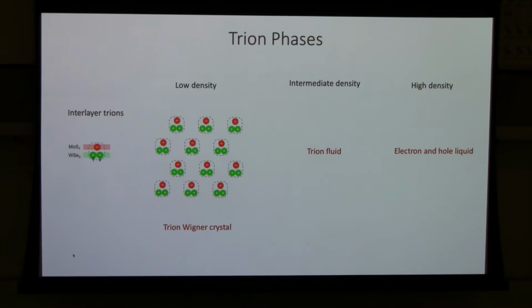So beyond the excitons, we can also inject electrons and holes with different densities. For example, if they have a 1:2 ratio, it was predicted they can form so-called interlayer trions, where you have one electron in one layer bound to two holes in the other layer. And these trions will be a charged particle, a fermion. So at very low density, just like electrons crystallize as an electron Wigner crystal, these trions are also predicted to form a trion Wigner crystal. And if you go to intermediate density, quantum fluctuations of these trions will melt it into a trion fluid.